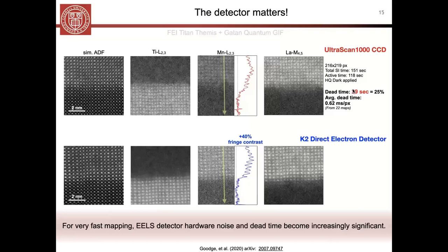And so that's sort of the total active time of the exposure. But then you can take, you know, when does it start and when does it really end? And that's sort of the total time. And so the difference between the total time and the active time gives you what we call the dead time. And so this is time that's passing. And if you're under cryogenic conditions, right, it's time that your sample is drifting, but time that is not contributing to any increase in signal, and therefore increase to your signal to noise or any of that.